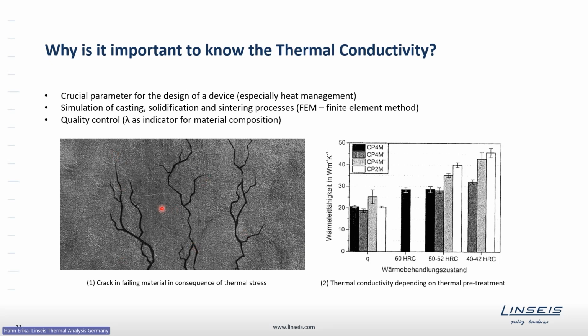So here, for example, you can see what can happen if the heat management is not designed very well, where you just get a crack in the material as a consequence of thermal stress, where maybe the heat is not brought away from the parts. Also, for example, in electronics, you need to make sure that the electronic parts do not get too warm. So you need to use a heat sink to bring away the heat from the electronics.